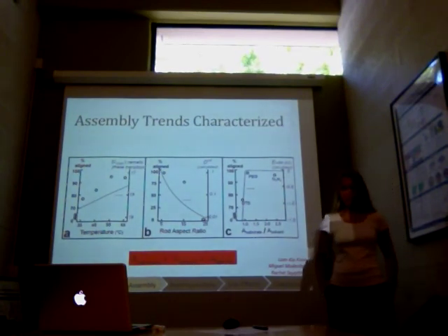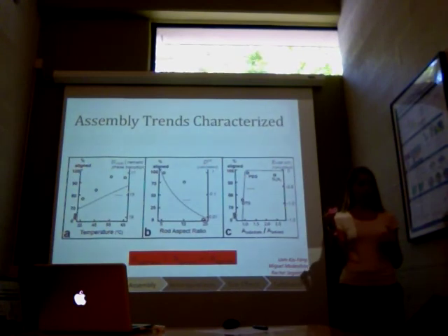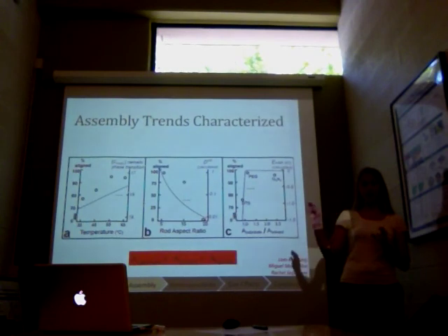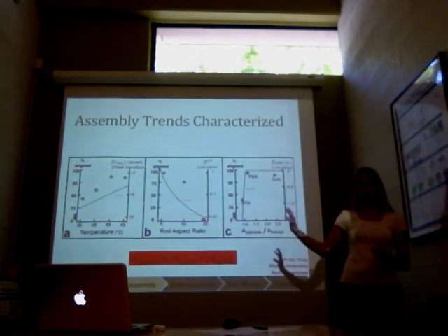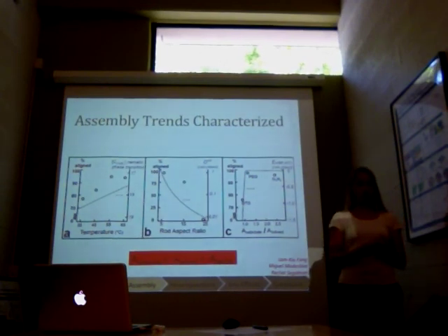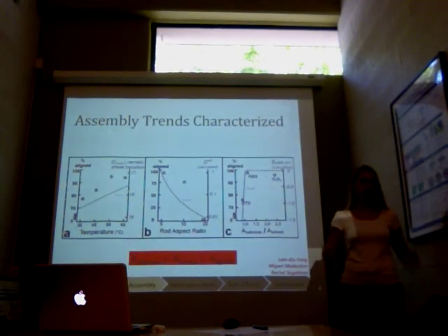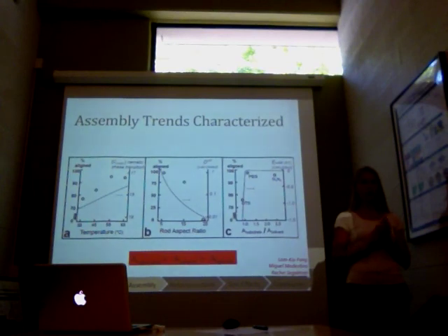So photovoltaic cells can get up to 50 degrees Celsius in the field. And so using very tiny copper sulfide nanocrystals, we would have a problem. Our electrical performance would be degraded for sure. Other than that, the organic ligands are stable at 50 degrees Celsius, so it's okay to heat them up that hot. And the crystals themselves are stable for more than hundreds of degrees before they melt. So as long as we're using nanocrystals that are greater than 5 nanometers in diameter, we're in a comfortable regime for the operating temperatures of solar cells.